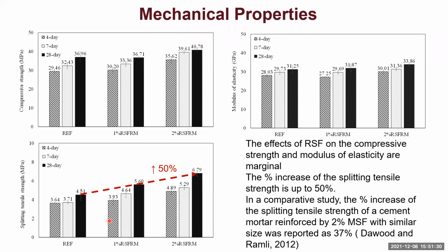And we also found a very similar study in the literature using manufactured steel fiber with a similar size to the recycled steel fiber used in our study. And we found that the split tensile strength improvement for the manufactured steel fiber was only 37%. As noted here, we can achieve 50% improvement. So we believe the recycled steel fiber could have equivalent or even higher fiber reinforcement effect compared to the manufactured steel fiber with similar size and similar dosage.